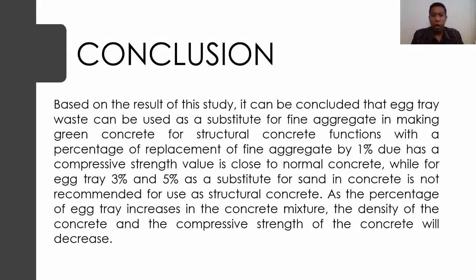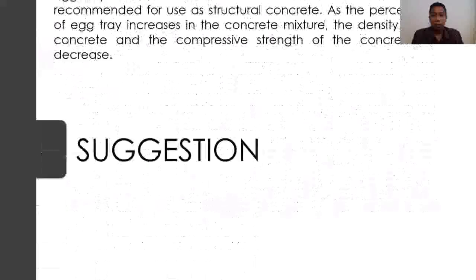Conclusion. Based on the result of this study, it can be concluded that egg tray waste can be used as a substitute for fine aggregate in making green concrete for structural concrete function. With a percentage of replacement of fine aggregate by 1%, the compressive strength value is close to normal concrete, while egg tray at 3% and 5% as substitutes for fine aggregate in concrete is not recommended for use as structural concrete. As the percentage of egg tray increases in the concrete mixture, the density of the concrete and the compressive strength of the concrete will decrease.